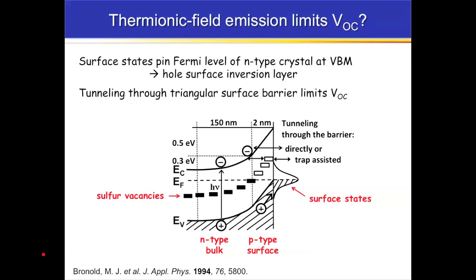It's the hybridization of field emission and thermionic emission. And if this happens, if this is really true, either direct tunneling or by trap-assisted tunneling, then you lose that 0.5. It's essentially totally lost. And then the maximum open circuit voltage that you would expect to get out is about 300 millivolts. And that is consistent then with what people are actually seeing in devices. And so the idea is that you have an N-type bulk and you have a P-type inversion layer at the